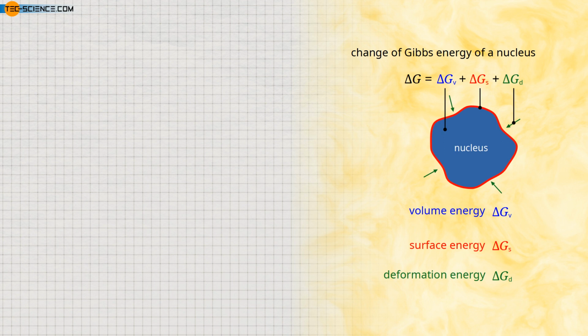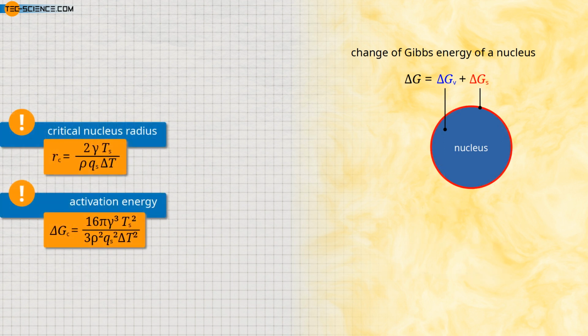Furthermore, it should be noted that the derived formulas for the critical nucleation radius and the activation energy are based on the assumption of a spherical cluster. In isotropic metal melts, this assumption is quite justified. However, for liquids consisting of long molecular chains, such as alkanes, a cylindrical nucleus is more likely to be assumed. It should also be noted that a spherical shape has the smallest possible surface in relation to its volume. A spherical cluster therefore shows the smallest possible activation energy for nucleation. For other nucleus shapes, the activation energy is higher.